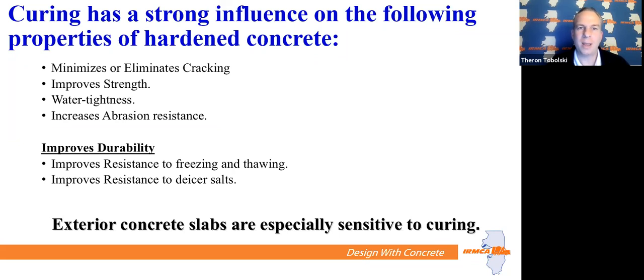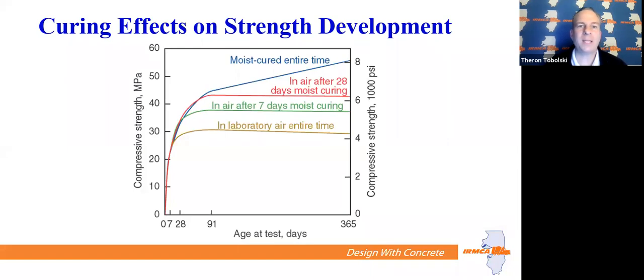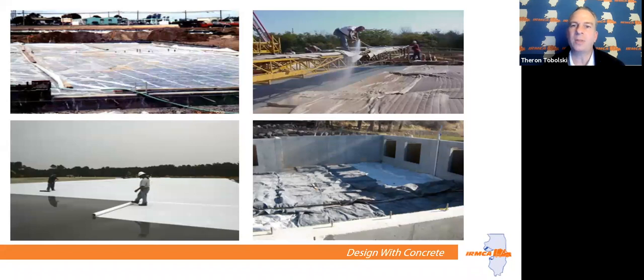It's really crucial that if you're an engineer and you're going with your contractor and talking about how he's going to handle the concrete, a curing method should be discussed and looked at. Effects on strength, right? If you see the brown line, a standard no cure could give you a 4,000 PSI mix. But if you take that same mix and you cure it with a moist cure for 365 days, you went from a 4,000 to an 8,000 PSI mix. So it just shows you that having the proper curing methods can really improve the strength and durability of your concrete mixes. And there are all different methods out there for curing.